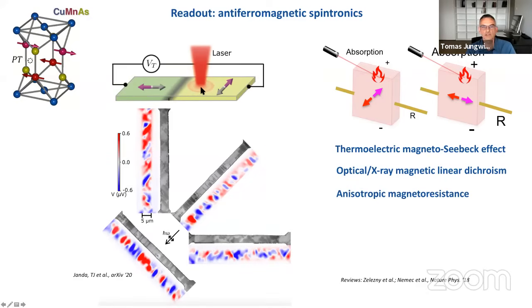So you can use it instead of going to a synchrotron for your X-ray imaging. You can do experiments in the lab with the focused lasers, and you can also image these antiferromagnetic domains. So here's an example of a recent work where side by side on exactly the same piece of material, you see the antiferromagnetic domains in copper manganese arsenide imaged in the lab by the thermal imaging, or at a synchrotron by the X-ray magnetic linear dichroism.